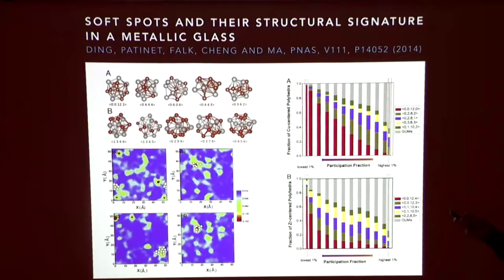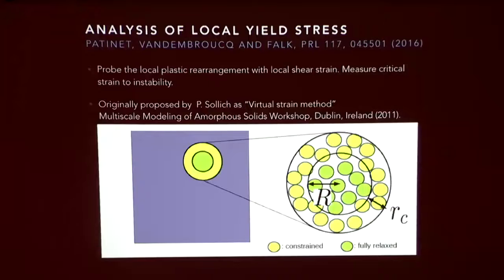But you can see the correlation is quite weak. The gray represents the very disordered structures, red represents the icosahedral-like clusters, and the participation fraction shows to what extent they participate in very soft areas. There's a correlation, but it's not enough to pinpoint where defects are, in my opinion. So let me jump into what we've been doing lately.